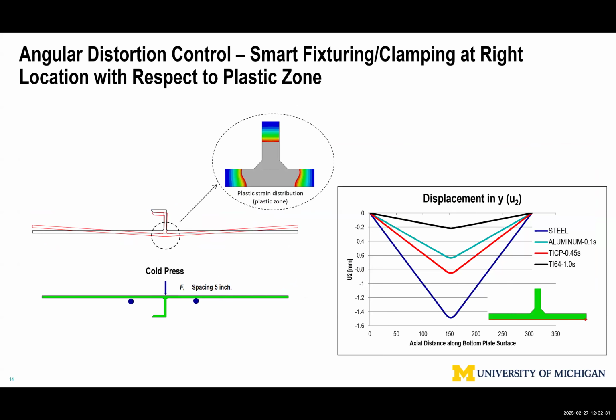The reason you produce that asymmetric deformation due to geometric asymmetry is the plastic zone, called the shrinkage zone. If we look at the T stiffener, L stiffener, on cooling it produces a natural shrinkage reaction. That shrinkage reaction only occurs within this plastic zone neighborhood. For the rest, if you plot this deformation from the bottom surface, what you see immediately, just like when you open a door, the hinge is the plastic zone, the gray color. The rest of the door is a rigid body rotating. That means if I do any clamping here, it doesn't do any good. Elastic deformation is fully recoverable. During welding, everything looks reasonable. As soon as you release it, they pop back.